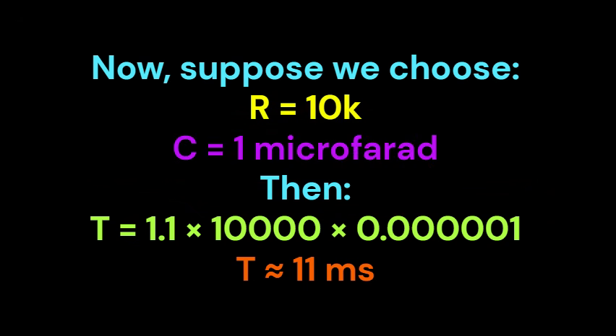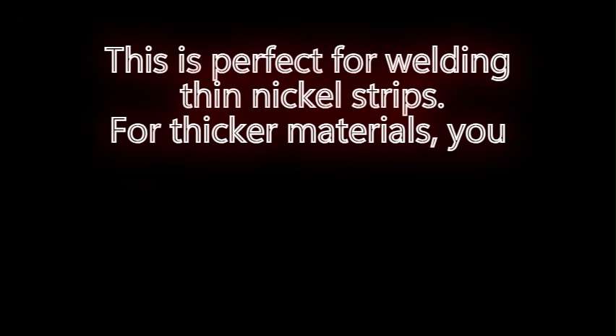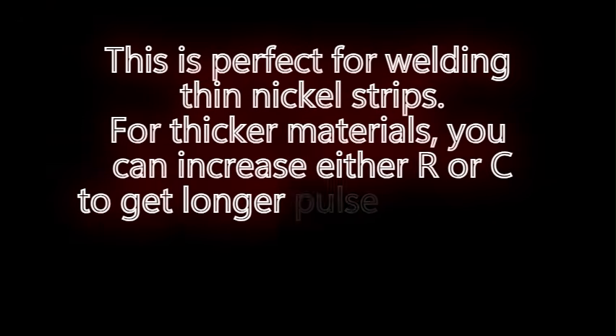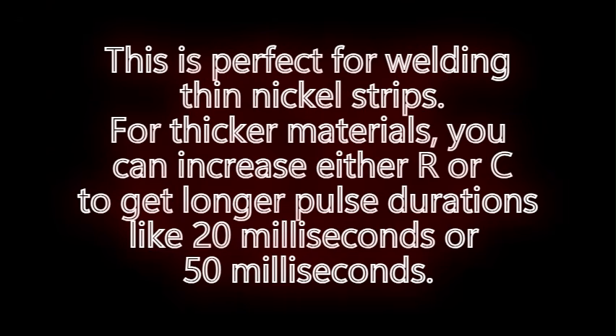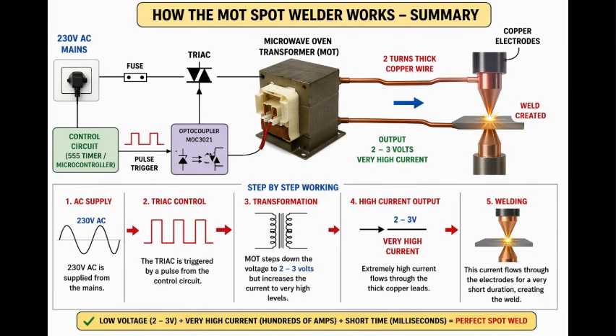Now suppose we choose R equals 10K, C equals 1 microfarad. Then T equals 1.1 into 10,000 into 0.000001. T is almost equal to 11 milliseconds. This is perfect for welding thin nickel strips. For thicker materials, you can increase either R or C to get longer pulse durations like 20 milliseconds or 50 milliseconds. This design is simple, powerful, and highly reliable compared to complex SMPS-based designs.